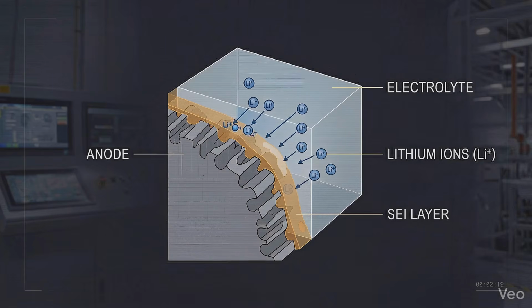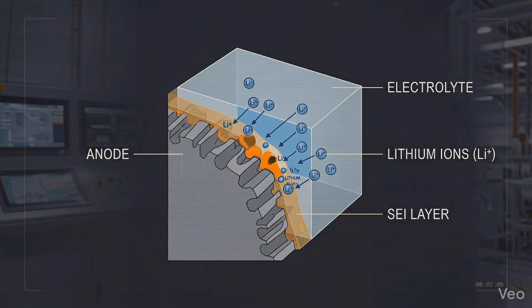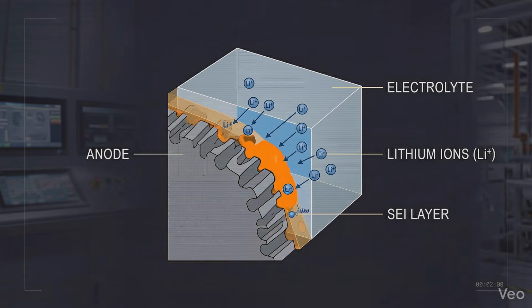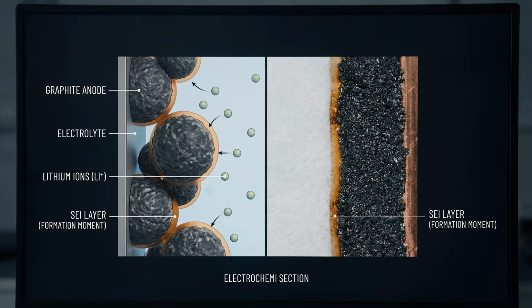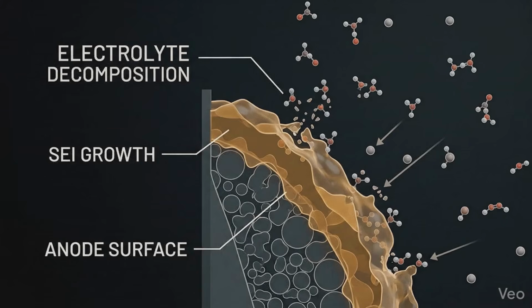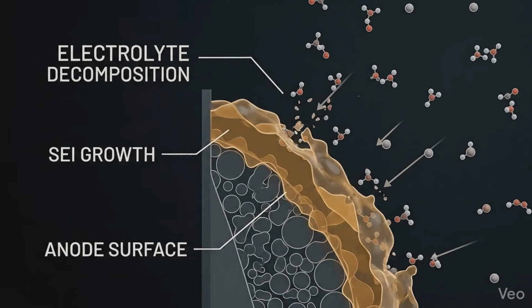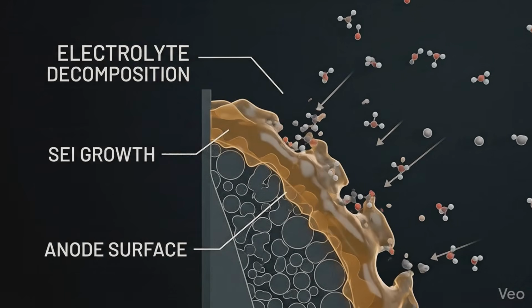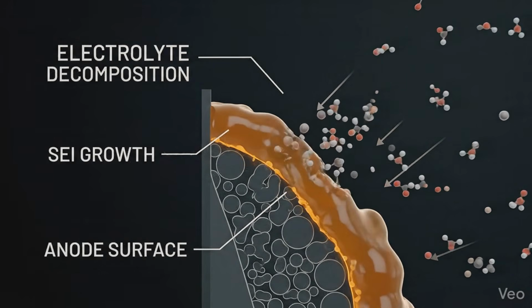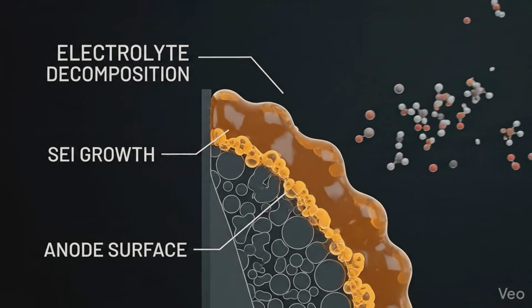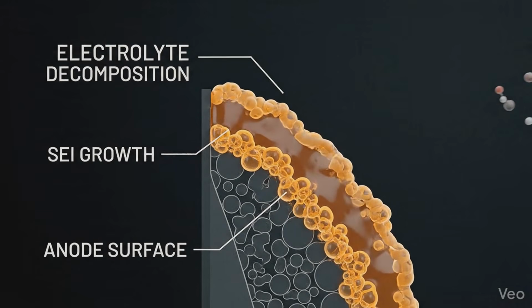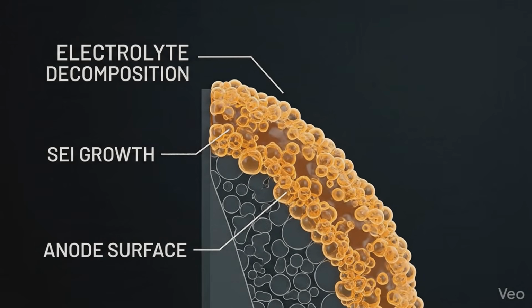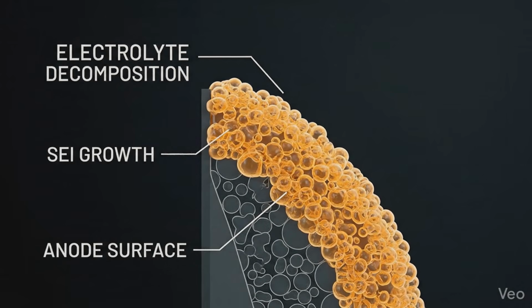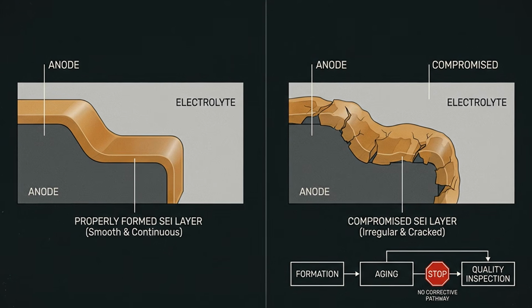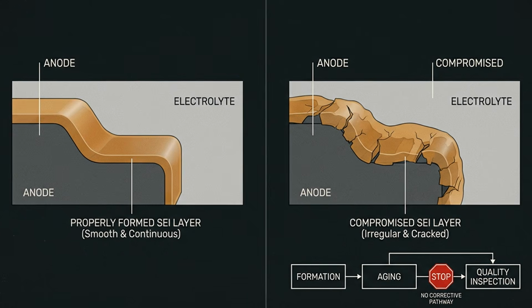During that first charge, a critical protective layer forms on the surface of the anode, called the solid electrolyte interphase, or SEI layer. This layer is not added by a machine. It grows from the electrochemistry of the cell itself, as lithium ions and electrolyte react at the anode surface. The SEI layer determines how the battery will perform across its entire lifespan, its capacity retention, its safety margin, its resistance to degradation. Get it wrong in formation, and no amount of downstream testing can fix it.